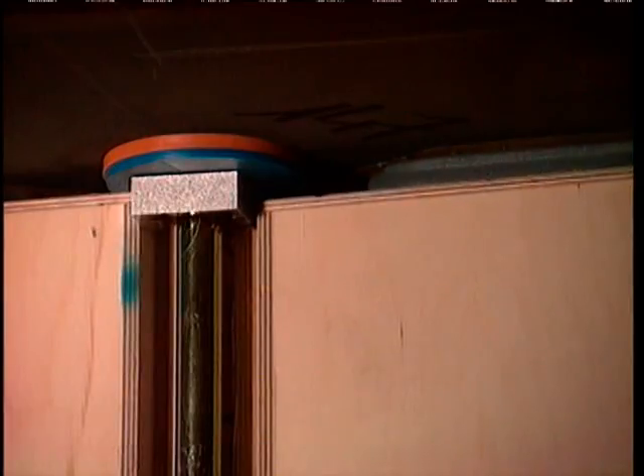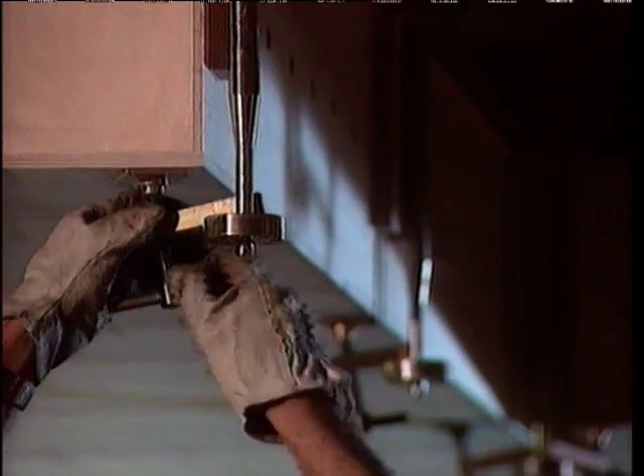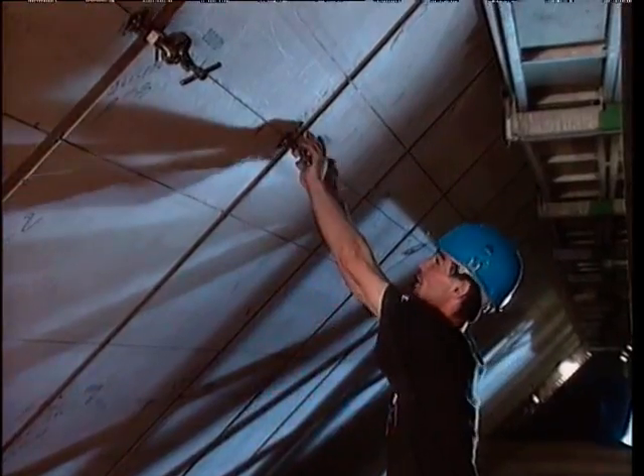The secondary boxes, each 300 millimeters thick with the resin rope coating, are set onto four adjacent wedges using manipulators. They're held in place with temporary devices until the precise alignment and flatness adjustments have been made. Following resin polymerization, the temporary fixing devices are removed. The boxes are permanently fixed onto the four corners by a plate nut and spring washers and coupler rod, which screw onto the previously welded base. The space between the boxes is filled with an insulating material made from foam or glass wool to limit heat convection.